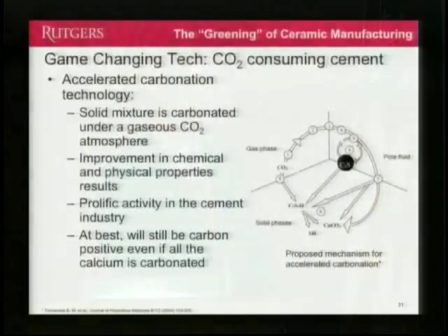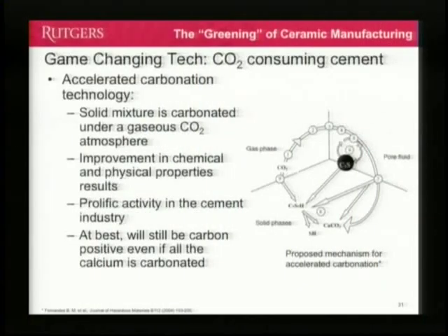And then there's another area of cement where people are calling this technology accelerated carbonation, where you're basically putting CO2 in a gas, and while the cement is curing, you're actually adding the CO2. And this is just a cartoon of the cycle for doing that. But there's no way you're ever, even if you put all the CO2 back in the cement, you still have all that fuel you've spent trying to heat that cement and make it a cement. So you're only going to cut the amount of CO2 at most by a factor of 2, but not get rid of it.